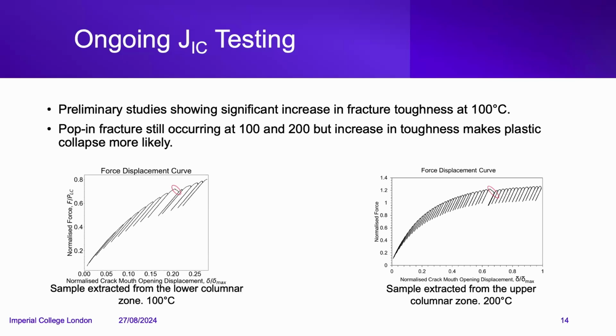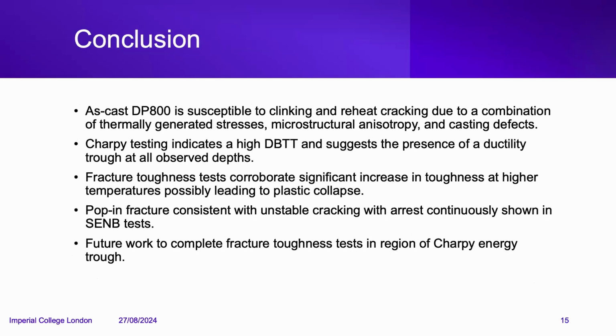There is a lot of plastic collapse happening for many of the tests that I've conducted at higher temperatures, and the crack sometimes actually does not grow. So that's also an interesting effect of temperature. But yeah, the aim is to complete those tests to the temperature range suggested by the Charpy tests, where a ductility trough may be occurring, to see if that is actually the case.